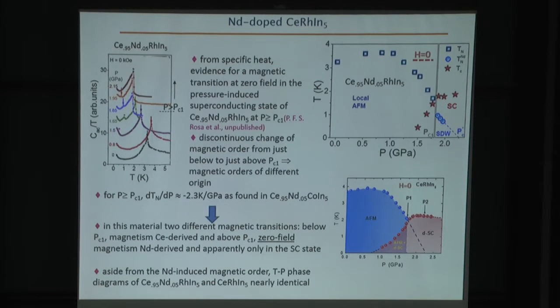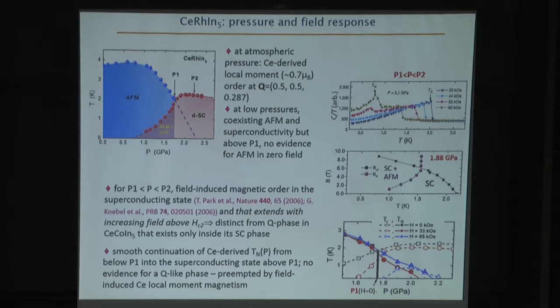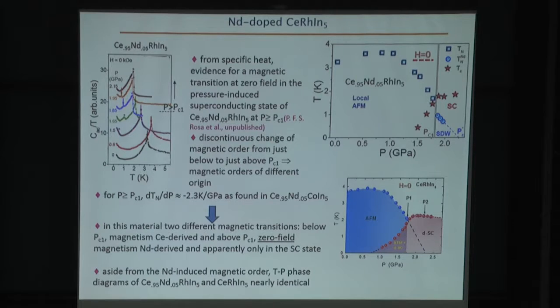So let me just back up. The maximum superconducting transition temperature under pressure in cerium rhodium indium-5 (CeRhIn5) is a little over 2 degrees. It's very close to the superconducting transition temperature of cerium cobalt indium-5 (CeCoIn5). We know that cerium cobalt indium-5 (CeCoIn5) is a d-wave superconductor. There's a body of evidence that suggests that the pressure-induced superconductivity in cerium rhodium indium-5 (CeRhIn5) is also d-wave.